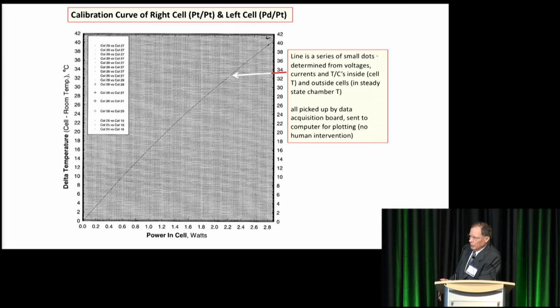So you could move it every 15 or 20 minutes, 3 or 4 times the time constant, and get a new data set. So you just bump this thing around until we acquired all the data that you see here on the curve. And I was delighted when I saw this. I was ecstatic. The precision in the power could be measured to plus or minus a half a milliwatt, and the delta T to 0.05 degrees C. So the power out had a plus or minus 15 milliwatt precision.